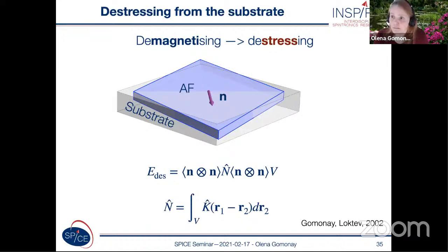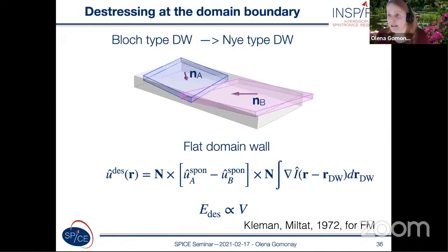So we tried to play with this idea and calculated, for example, the so-called distressing energy. And this is energy which has its analog in ferromagnetic materials. In ferromagnetic materials, we calculate demagnetizing energy, which should be zero if the average magnetization of the sample is zero, and similar can be demonstrated for antiferromagnets grown on non-magnetic substrate. The distressing energy scales with the volume of the sample and should be minimized when all the domains with different deformations are equally represented.